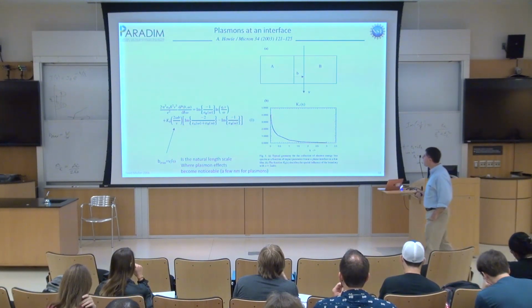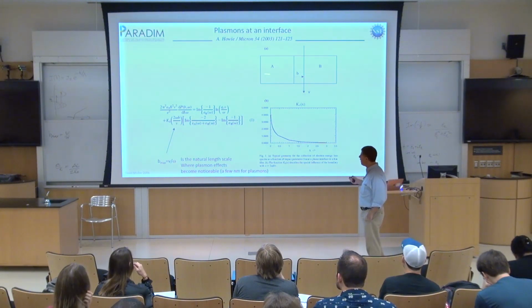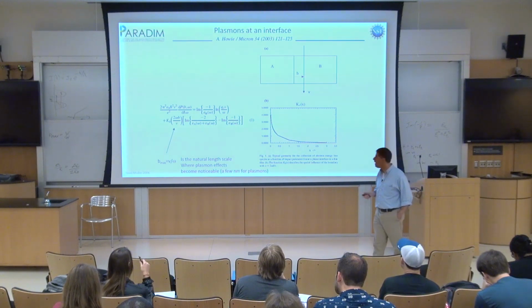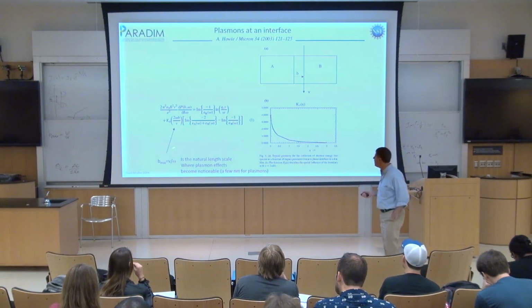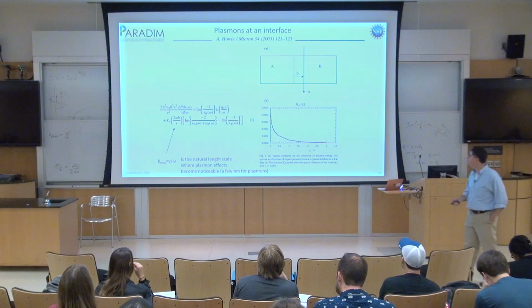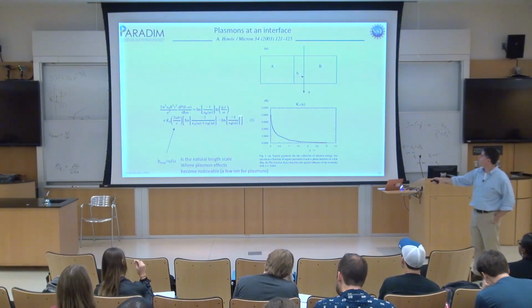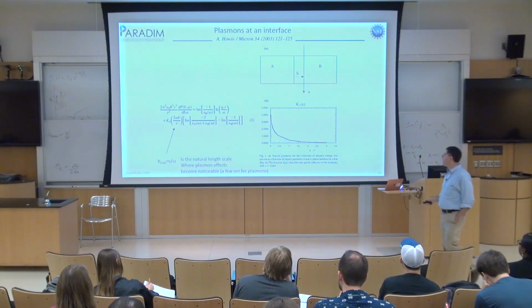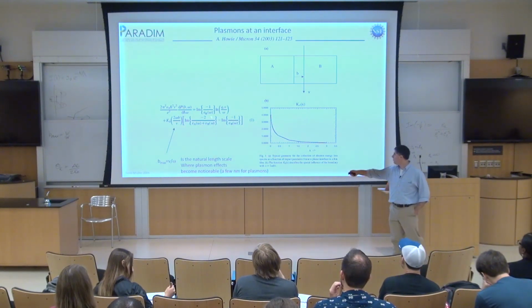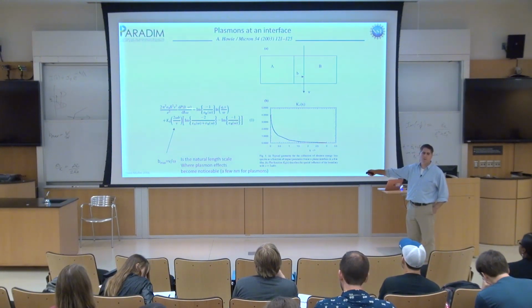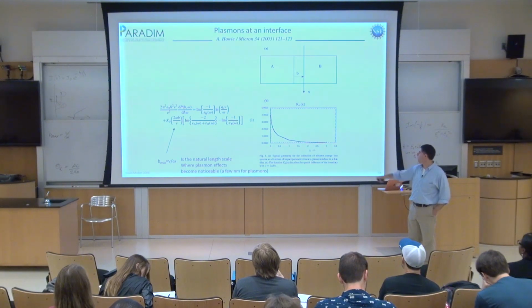And then you go back to Jackson and solve the boundary conditions for the problem. And the solution you get is this energy loss function. There are 2 terms. This is the energy loss in material B. There's a bulk term here, which will dominate when I'm very far away. And then there is an interface term, which would be the minus 2 over epsilon 1 plus epsilon 2, or 1 when that material was in vacuum.